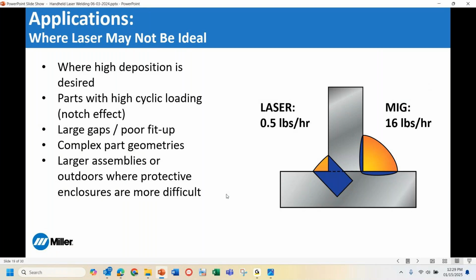The first thing that's really going to be a driver behind that is the amount of filler metal that we're providing or depositing with the handheld laser process. With our system, we're depositing about a half a pound per hour. I've seen some systems in the market where they might be running multiple wires. Realistically, you're still sub 2 pounds per hour, typically sub 1 pound per hour of deposition rate. And when we compare that with conventional welding processes, a typical mature or proven out MIG welding operation should easily be depositing 15 or 16 pounds per hour.